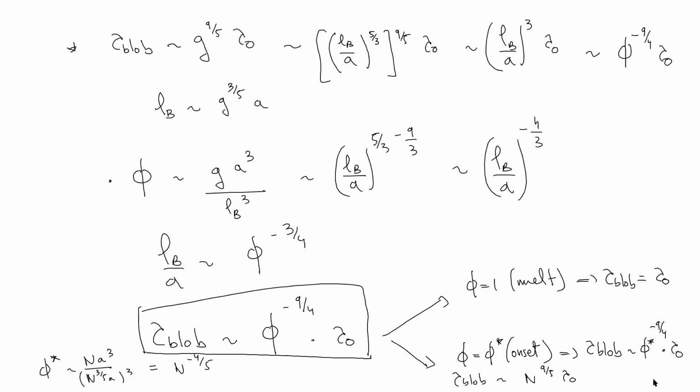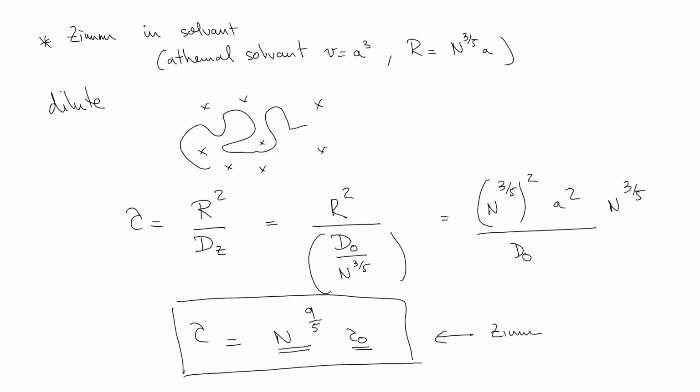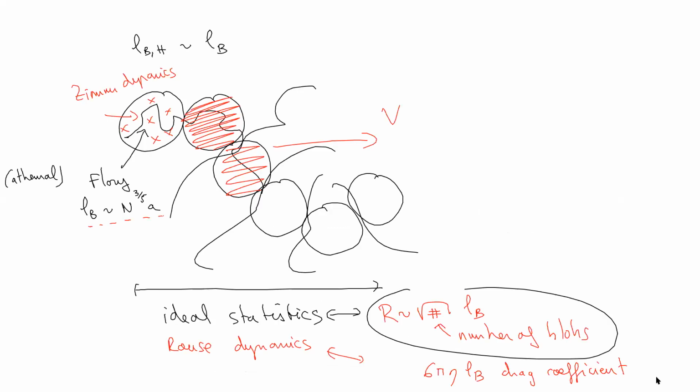Okay, so now you understand solutions pretty well. The very big step here that you have to keep in mind is this one. We identified the length scale for the screening of the static interactions, meaning the conservative potentials, van der Waals, for instance, or repulsive barriers and so on. And the length scale for hydrodynamic interactions, meaning if I move in a fluid, I will displace the fluid around, and this will move solvent molecules with me on a certain length scale.